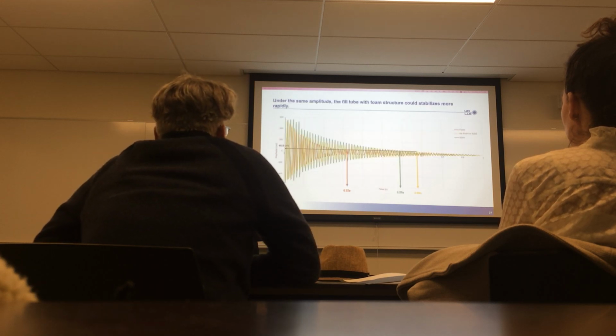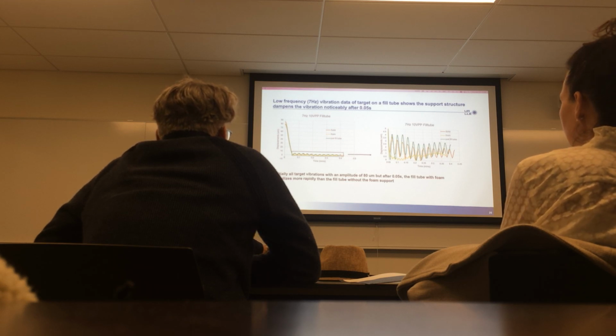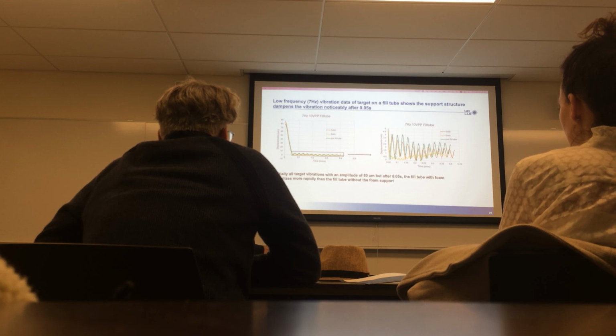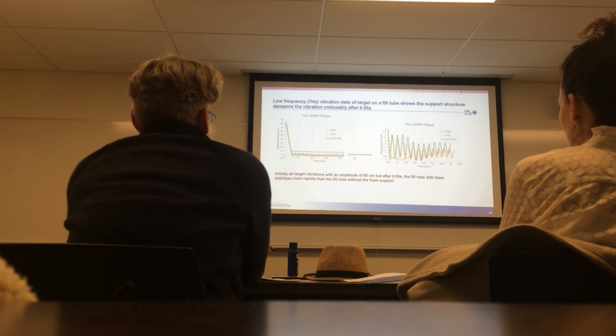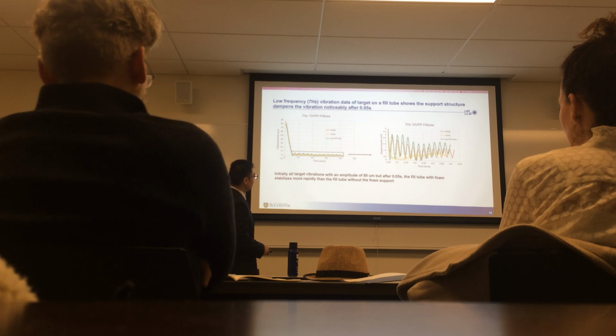Okay, when we do the vibration test, at first we just use the low frequency to vibrate the target structures. We vibrate the target structure at 7 Hertz, with a 10 voltage amplitude. So the target will start shaking at 80 micrometers displacement. But after 50 milliseconds, the fuel tube with the foam structure, the displacement was limited to half a micrometer. And the fuel tube without foam structure still has the 2 or 3 micrometers displacement, which means the foam structure definitely dissipates some energies and limits the fuel tube at a low frequency. So in the low frequency, the foam structure works.